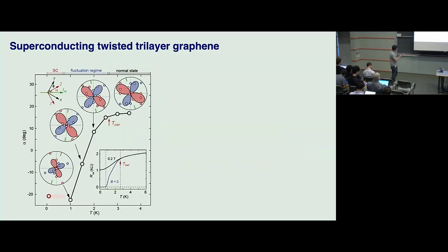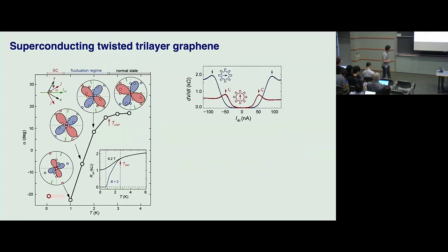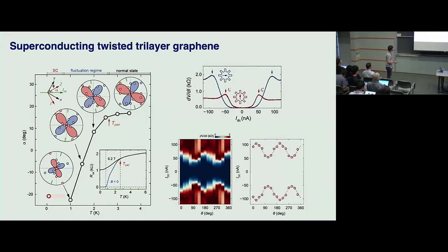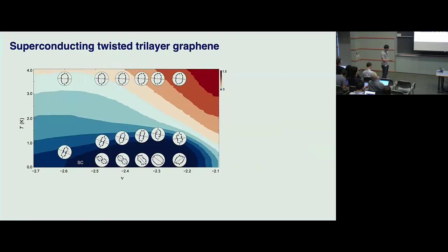In this system, we can directly probe superconductivity by doing IV measurement, right? For example, these are two IV curves measured with current flowing in two orthogonal directions, and you can clearly see that the critical current varies by a lot, right? All of these are done at B equals 0, so there's no influence of B. And in fact, if I plot the color plot of all the IV curves put together, extracting the critical current from the peak in the differential resistance clearly gives you this cosine 2 theta dependence that defines the easy axis for the superconducting phase.